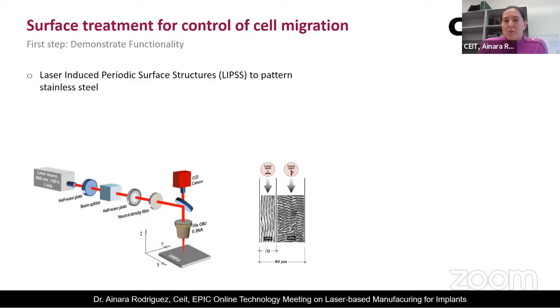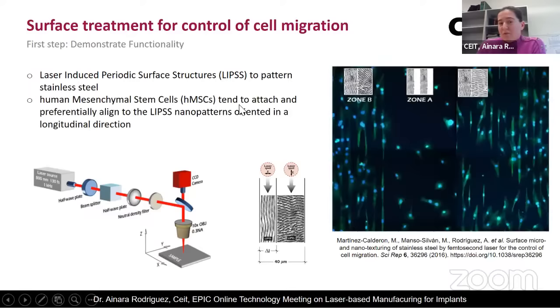So the first one was, let's say, the first demonstration of surface treatment through femtosecond lasers that could control the cell migration on metallic implants. So what we do is basically to texture the surface of the metallic implant. In this case, it was stainless steel, but we have done it also for titanium alloys. So we texture the surface with a single pass of the laser beam, and we obtain these, let's say, self-ordered structures that are very small, less than 1 micron, and we produce what is called laser-induced periodic surface structures. So we can control the order or the movement of the different cells on the surface by controlling which type of structure we generate on the surface.